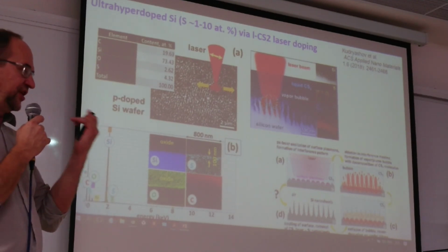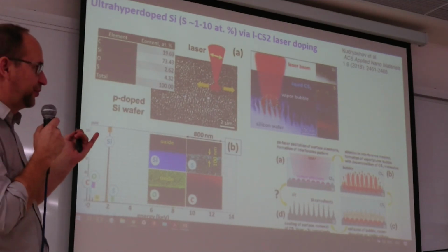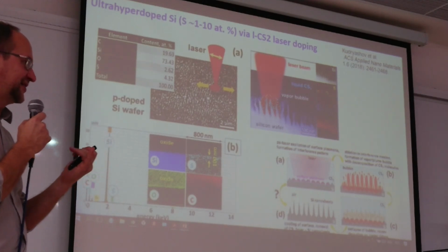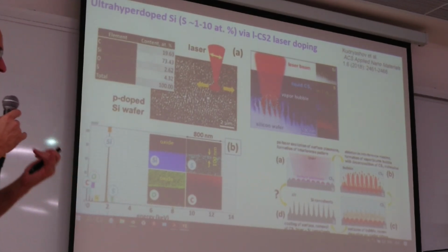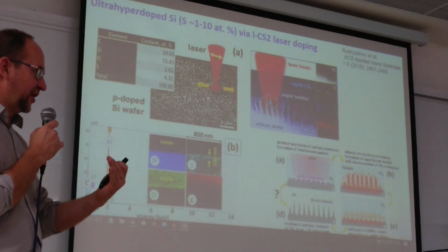This is almost 10 times more than the technology developed by Harvard University, because they have used gases. Gases are less dense compared to liquid, almost 1,000 times less dense. So collisions of doping molecules with the hot surface occur almost 1,000 times more rarely. And so this technology is more intense in the sense of sulfur doping inside silicon. As a result, we can introduce much more sulfur inside, almost 10 times more. As I told, 4 atomic percent in this case, but in some cases up to 8%.